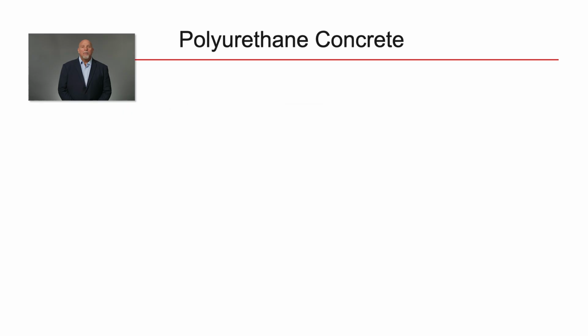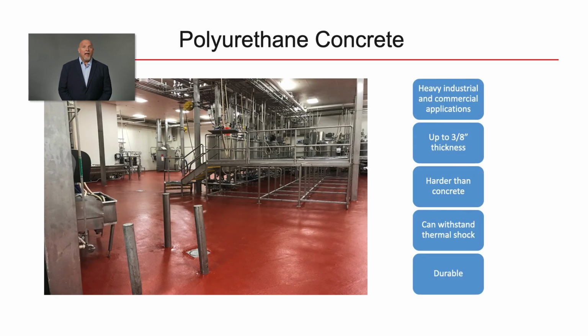Polyurethane concrete. Polyurethane concrete systems are used for heavy industrial and commercial use applications. These types of floor coatings are applied in thicknesses up to 3/8 of an inch and can be twice as strong as concrete. Polyurethane concrete is much harder than concrete, with a pound-force per square inch strength reaching 7,500 psi or more. Polyurethane concrete systems can withstand the thermal shock inflicted by a range of weather conditions and the force of hot or cold high-pressure washing.